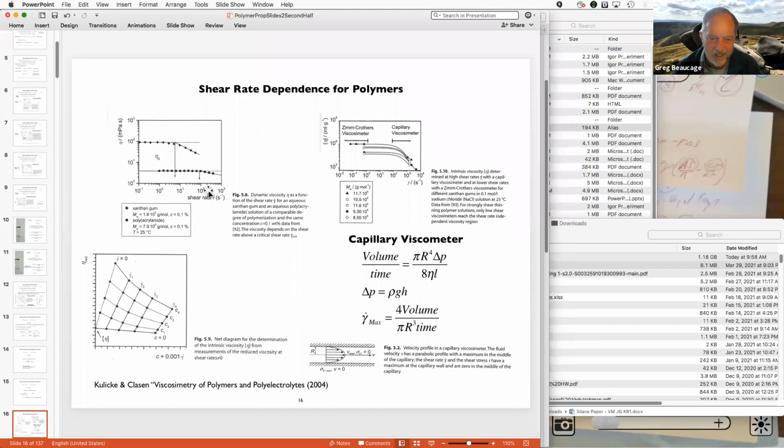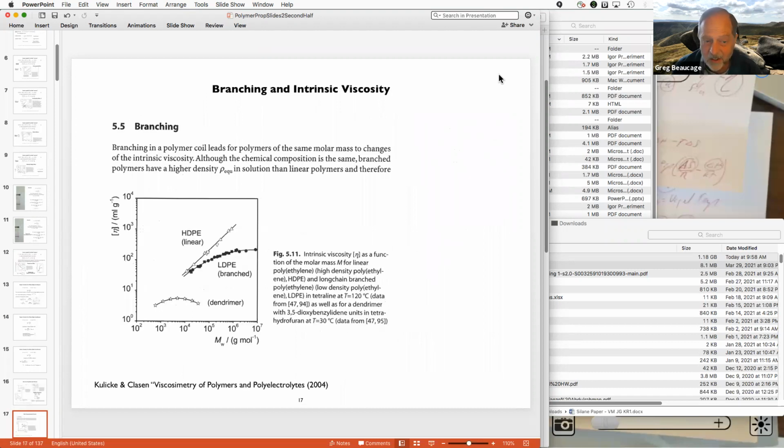So this capillary viscometry, unless you're going at very slow flow, is not an optimal technique for shear thinning fluids, but it's simple to do. People just do that, and they assume that all the mismatched things get washed out because you're just measuring the time and you divide by the solvent time.